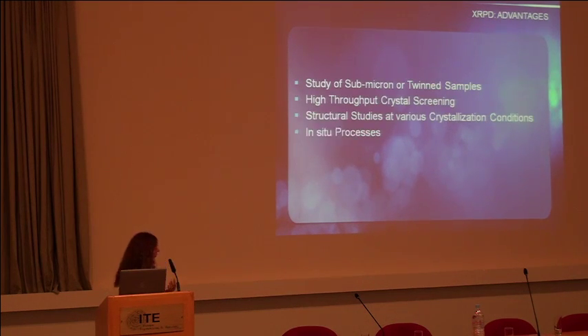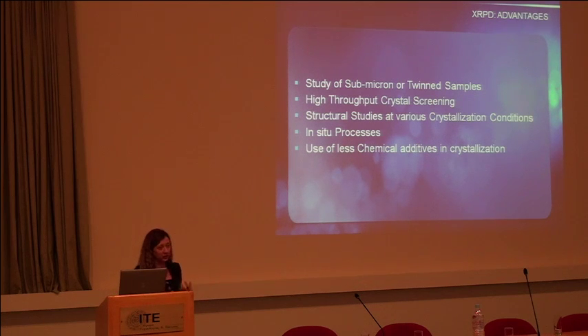The advantages of the method are several. First of all, we can study very low quality samples, sub-micron crystals, as I already mentioned, twinned or mosaic crystals, because we don't see these defects. It's an ideal method for high throughput crystal screening, because data collection is very quick, and also preparation of microcrystalline precipitates is much easier, from what we've seen over the last decade.